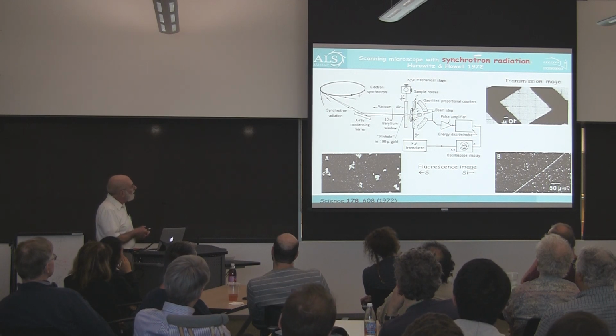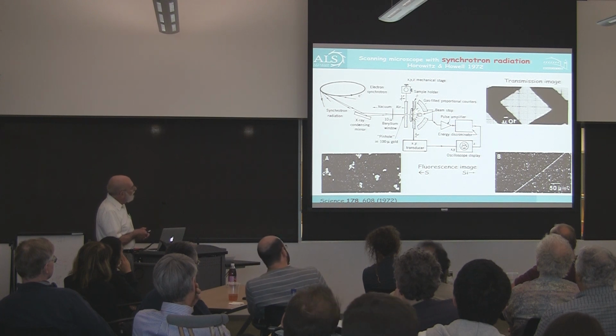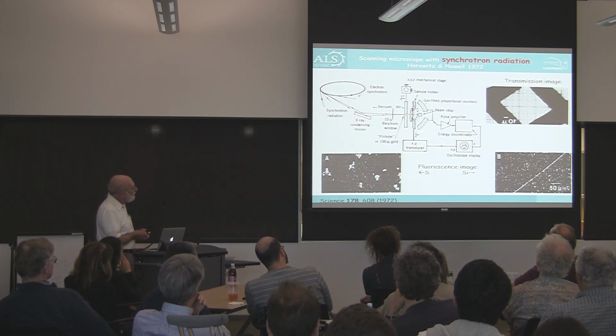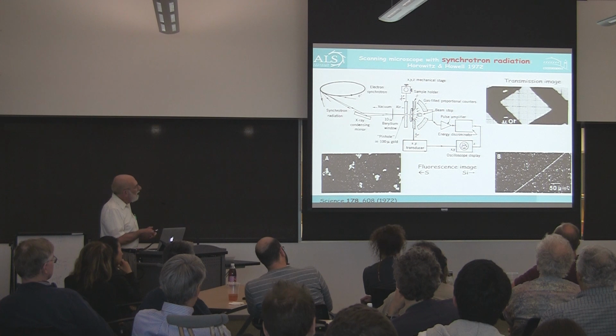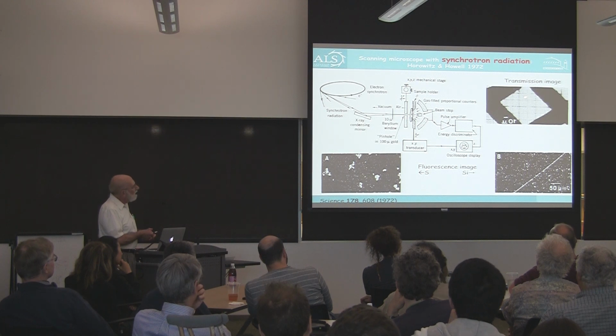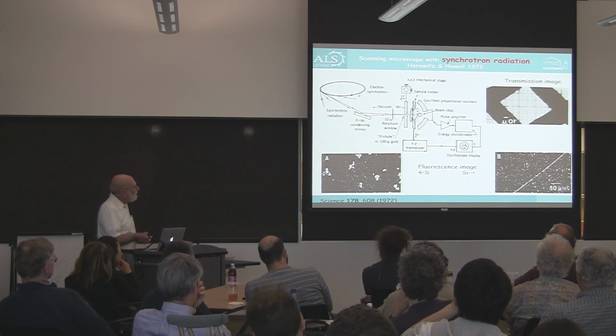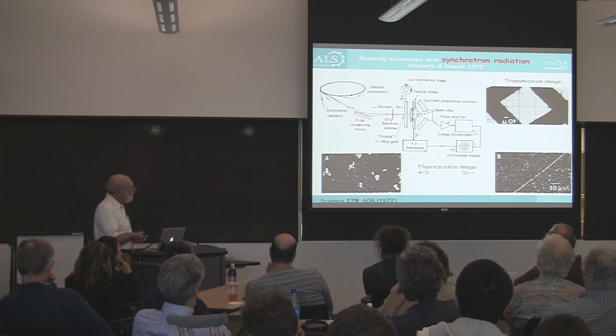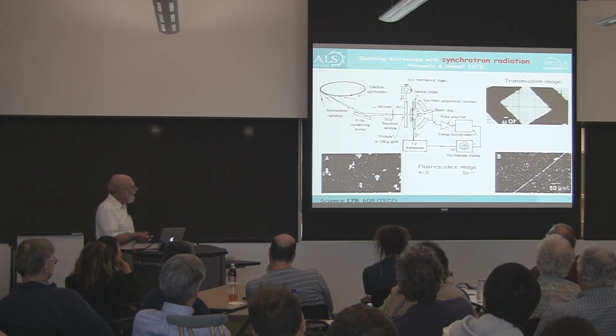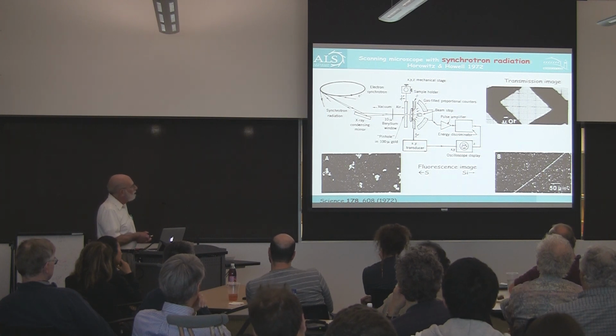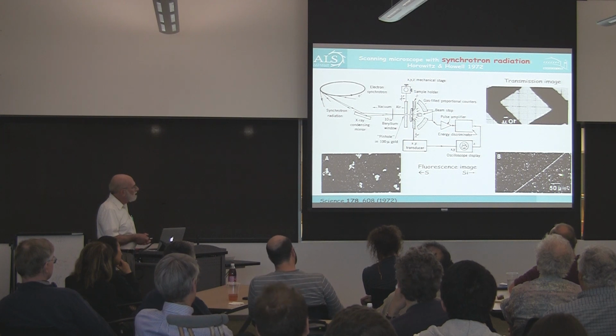They used Horowitz and Howell at the Cambridge Electron Accelerator, scanned their samples with this micron-sized probe, and detected either the transmitted radiation or fluorescence radiation, and demonstrated that in transmission, an electron microscope grid could be imaged with micron-sized resolution, or by using fluorescence, they were able to find little sulfur granules or a silicon whisker by using the characteristic X-rays. Notice the scale bar here is 50 microns and here it is 10 microns.